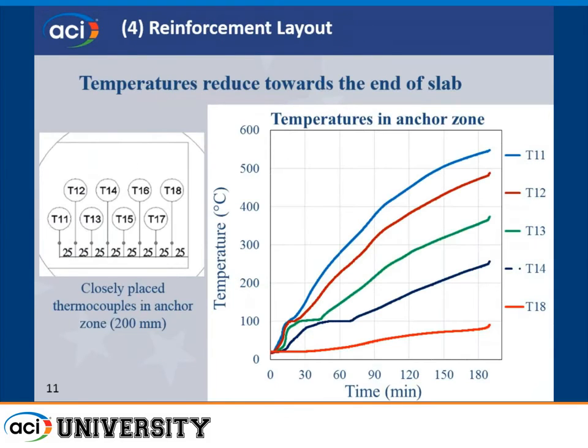But one of the things that we did is we know that the issues relate to the bond, because we know that the bond of the FRP to the concrete is dependent upon that polymer. And the polymer is what is affected quite readily by the high temperature. So this is in those 8 inches at the end, and we're looking at the temperatures there. So this little portion, these 8 inches at the end, not exposed to the fire, and so we have much lower temperatures during the fire exposure.